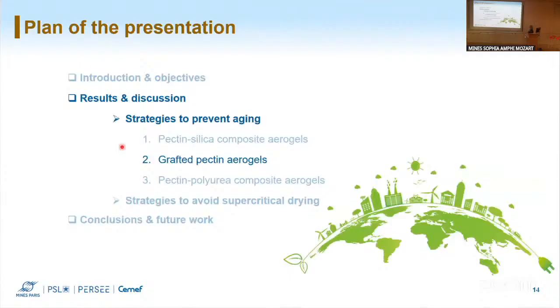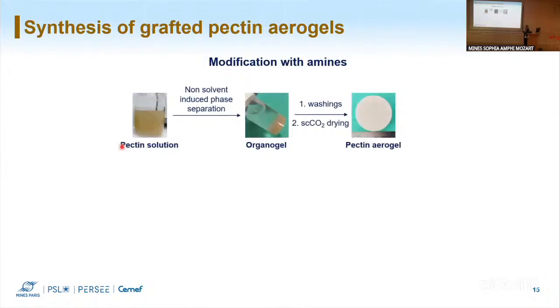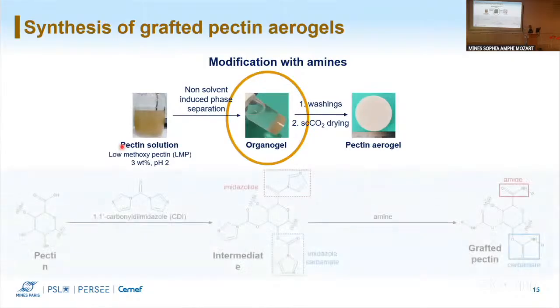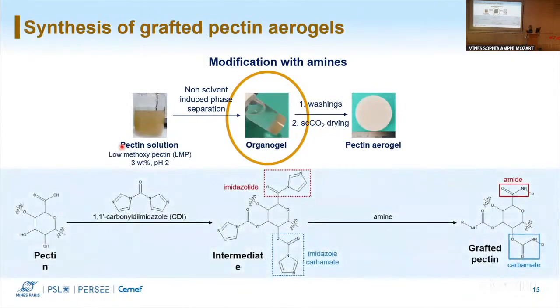Now, the next approach that we had is to modify aerogels, to graft the aerogels, and this was by modification with amines. In the general scheme, now we've worked with the organogel, so we are in heterogeneous reaction, and we used low methoxy pectin at 3 weight % and pH 2 from the initial aqueous solution. Here we can see the reaction that is performed. So first step reaction was carbonyldiimidazole to activate the functional groups of pectin. And second step, we add an amine.